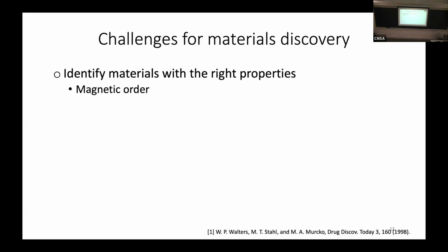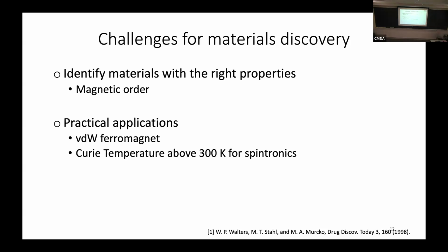So again, it's challenging because you have to identify the materials with just the right properties. In this case, you have to find materials that have magnetic order. Of course, you often need to have multiple criteria satisfied. So to be industrially relevant, you should have a Curie temperature above 300K. Curie temperature is the temperature below which the spins align, above which they will be randomly aligned.